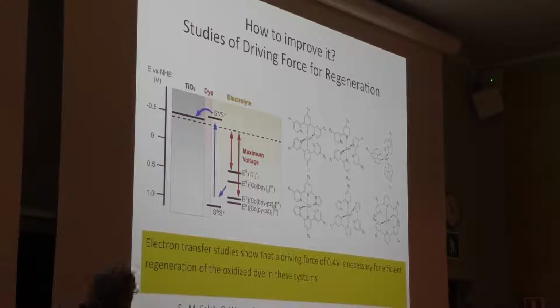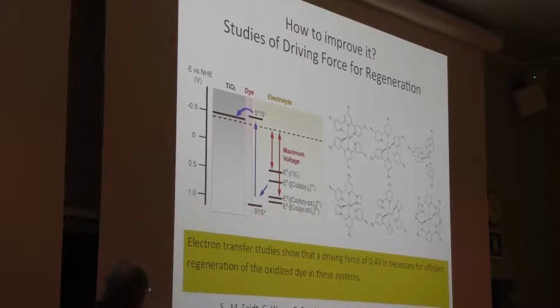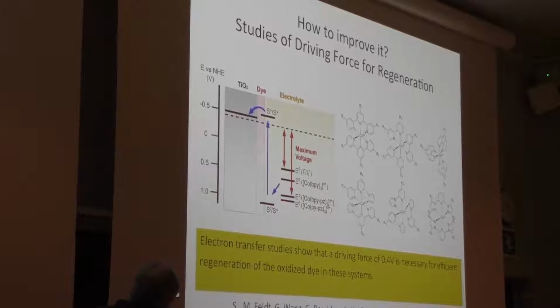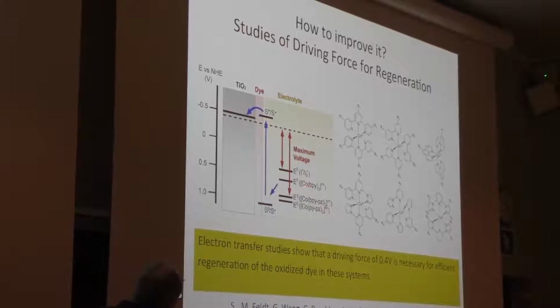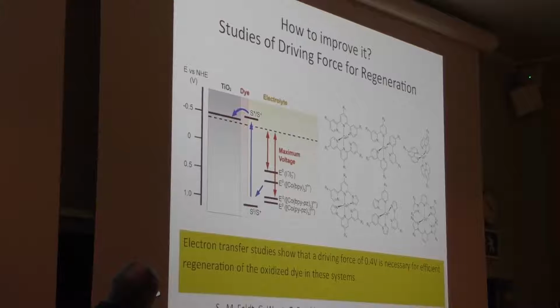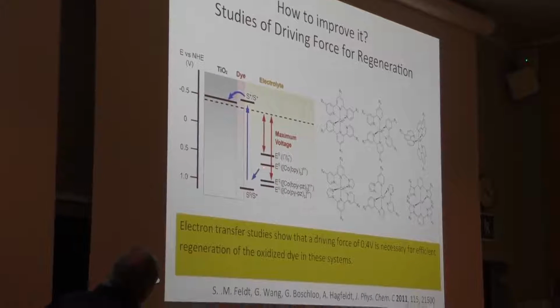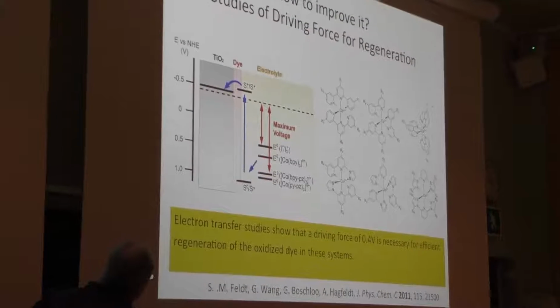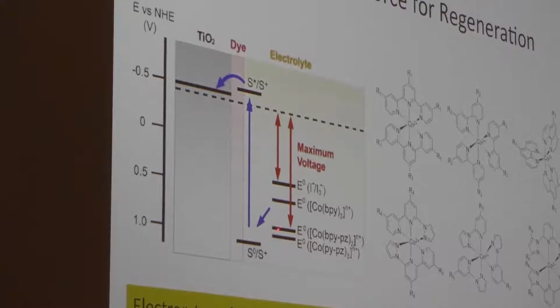We had 0.7 volts needed for iodide. Can we do it lower with the cobalt? And you see here the sketch. This is now the difference in driving force with the redox potential, because you can tune the redox potential of cobalt with the ligands here. So you can really have a nice window of redox potentials, decreasing the driving force.